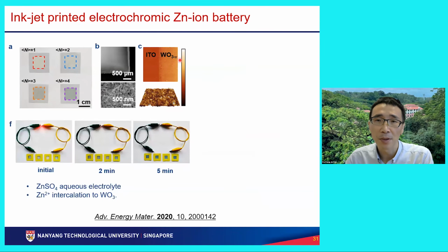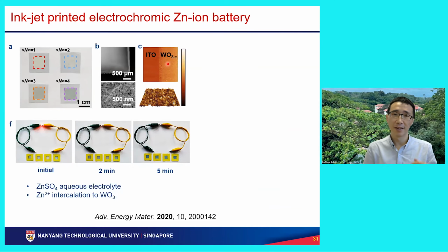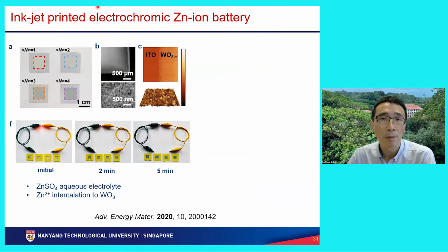In addition to the battery just mentioned, we can also print. Rather than just using hydrothermal growth, we can also print the batteries on a substrate. For example, this one is inkjet printing of tungsten oxide on the surface of an engineered zinc surface, and then we have a layer of sol-gel electrolyte, a quasi-solid, and then ink on the tungsten oxide.